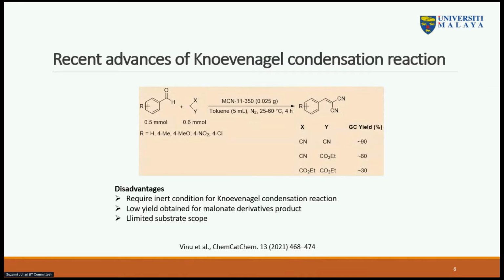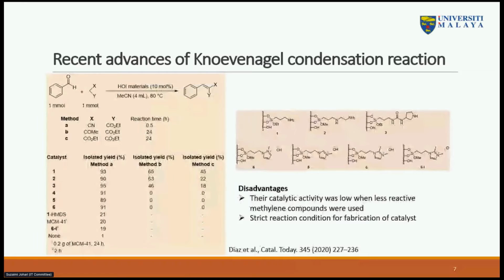And also, it's facing some disadvantages from this work because it required inert conditions, which is very sensitive to air and moisture, and also, as I mentioned, it produced quite low yield for malonate derivative products, and also the substrate used for this Knoevenagel condensation reaction is quite limited. Also, we can see here another different kind of metal-free catalyst that has been used recently in 2020, using the hybrid mesoporous silica.